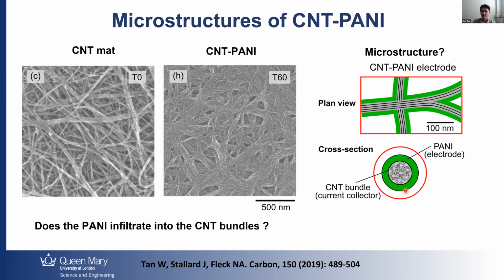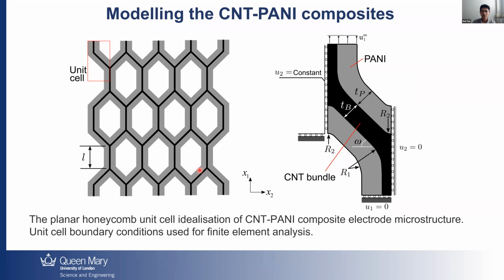The question is, does the PANI actually infiltrate inside the CNT bundles? The answer is no. In one of our papers we published, we have proved that the polymer is hard to penetrate into the CNT bundle, with the gap being tiny, nanometer size, and it's only able to coat on the surface of the bundle. So with that evidence, we can actually model the CNT-PANI composite like this.